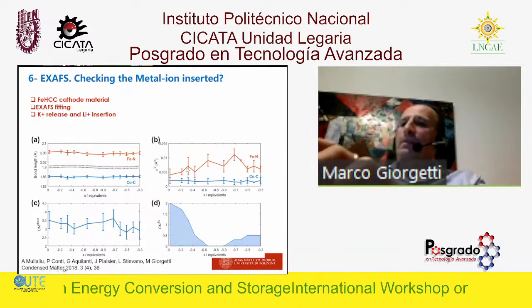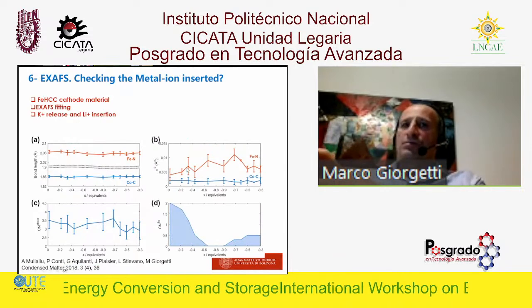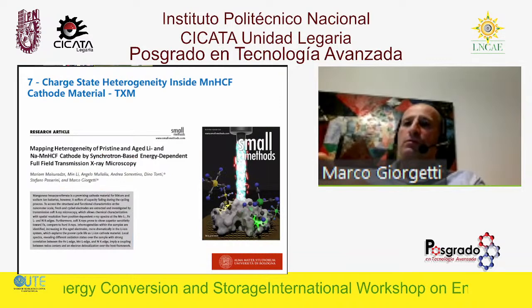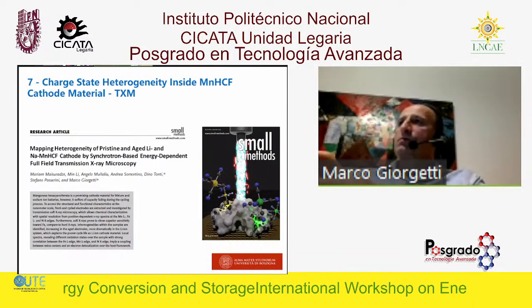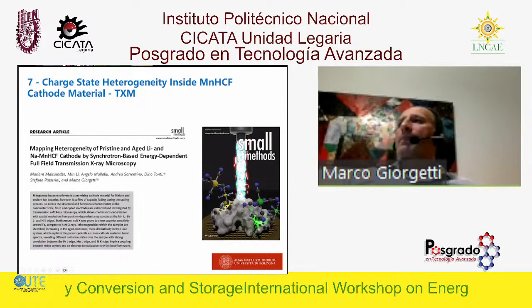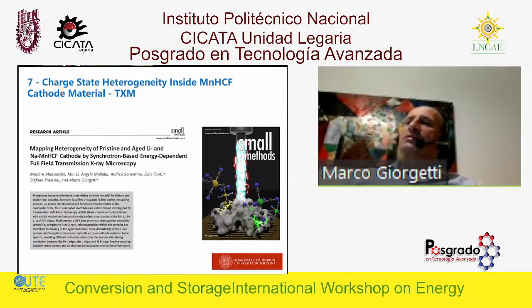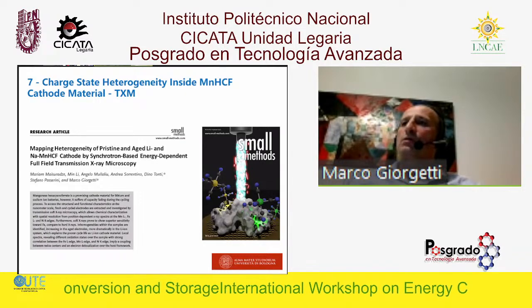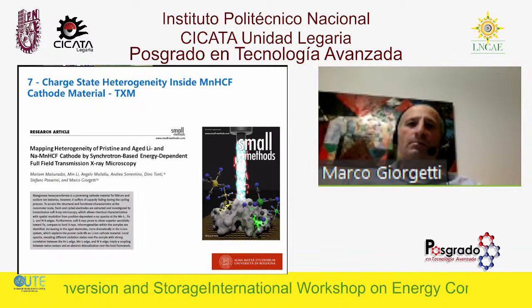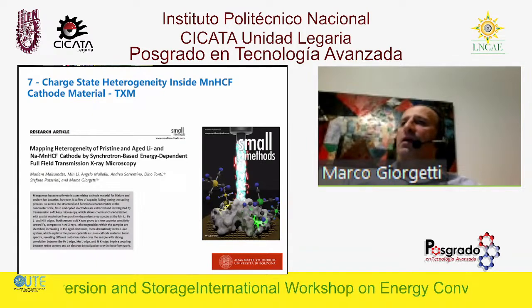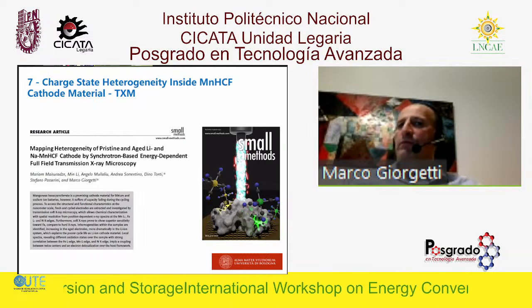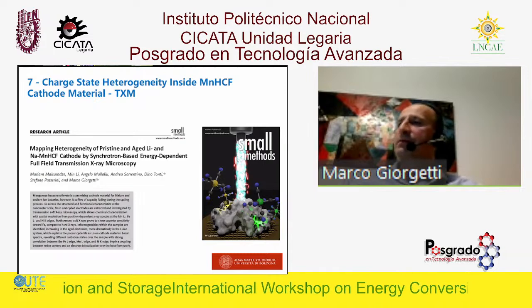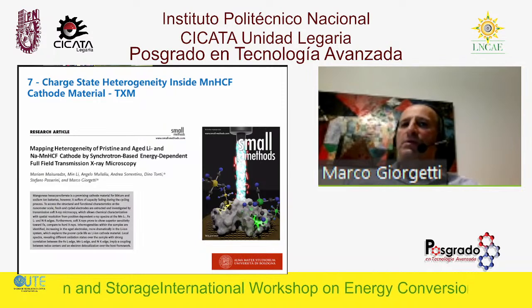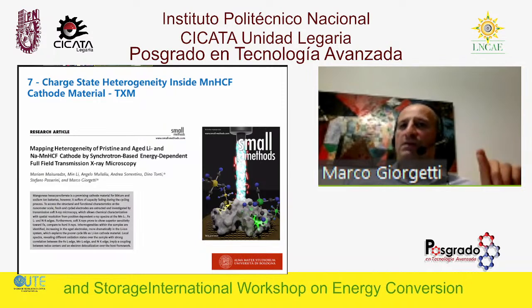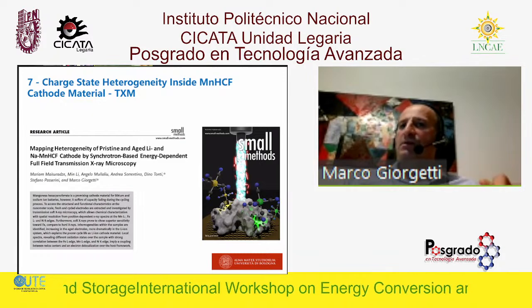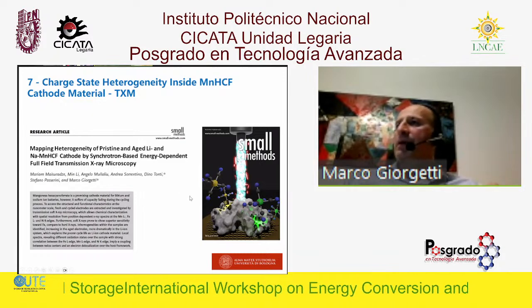I just want to skip this, and then go to the next measurement. Since we were interested in this manganese as a sodium-ion battery cathode, we were also interested in conducting some microscopy experiments. And one of the techniques we adopted is full field transmission soft X-ray microscopy, which was able to give a full picture at the nanometer scale of the chemical states and the spatial distribution of elements inside the manganese cathode.